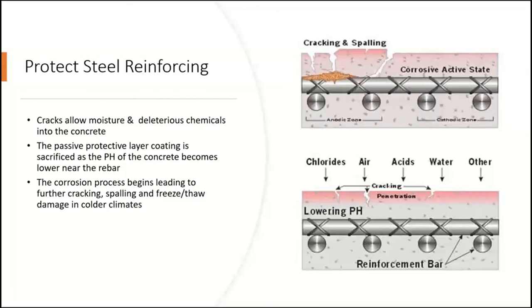Part of the reason has to do with what can happen with the corrosion of the reinforcing steel. The way that this works is we have a certain amount of cover over the reinforcing steel. You have de-icing chemicals, chlorides, atmospheric pollutants, and things like that getting into cracks. And what happens is the pH of the concrete starts to lower around that reinforcing steel. It starts out around 12.5, and that forms a passive protective layer around the steel. And once you start lowering that pH, you create an environment in which that reinforcing steel can begin to corrode.